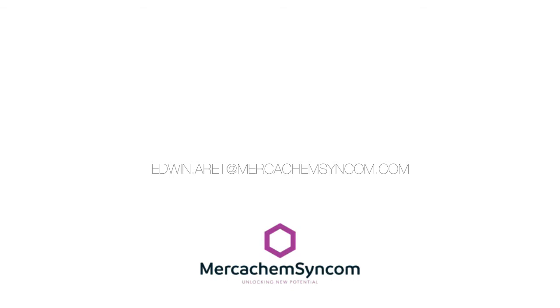Polymorph prediction software has developed greatly in the past years. Could this replace the many screening experiments and selection process? No, it will not replace it. It's additional to that one. So the advantage of a prediction is you know which one is actually the most stable one. But the disadvantage there is you need to make it, so you don't know how to produce that form. On the other hand, screening, it is possible that there is a more stable form there that you didn't access yet by the normal ways of the screening that you do. So the combination of the two, that will be the most strong conclusive form to take.